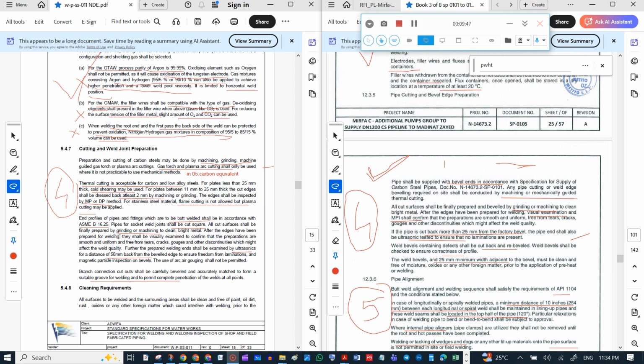All surfaces will be prepared by grinding or machining to clean bright metal, and prepared welding ends shall be examined by ultrasonic for a distance of 50 mm back from the bevel edge to ensure freedom from laminations, and magnetic particle inspection on bevels. Use of arc air gouging shall not be permitted. Branch connection cutouts shall be carefully beveled and accurately matched to form a suitable groove for welding to permit complete penetration of the welds. So this is also completed.